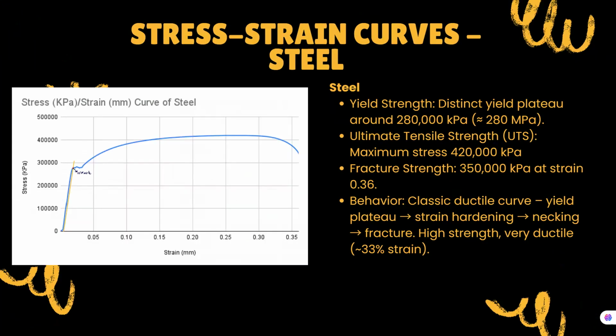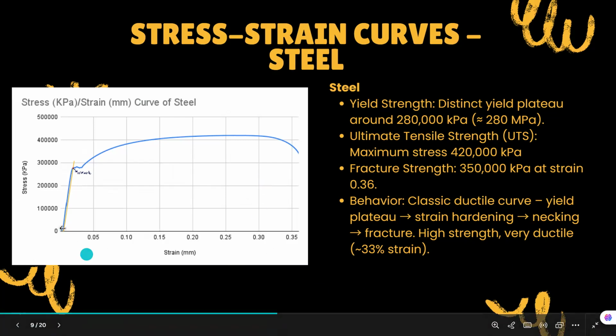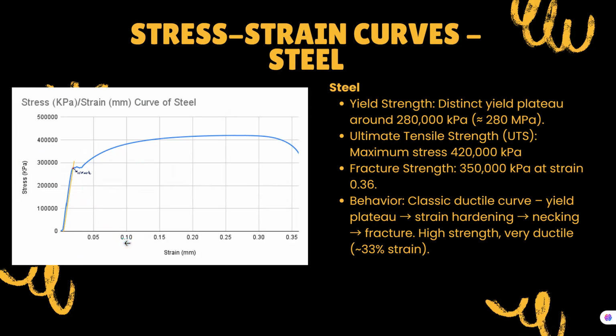And here's the graph. The graph here is shown for the steel, and we can see that the yellow one is the offset, and from the offset line, we can see the intersection, which is the red dot here. It shows around 280,000 kilopascal, and for the ultimate strength, it is 420,000 kilopascal at the highest point, and the fracture strength here is 350,000 kilopascal at strain 0.36.